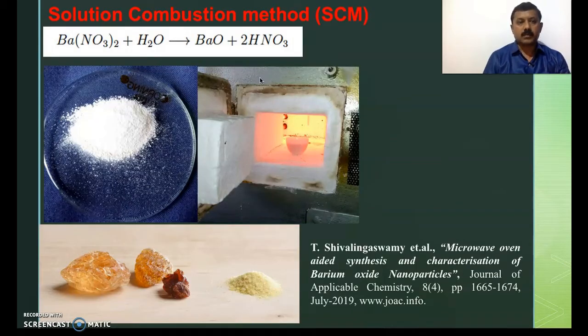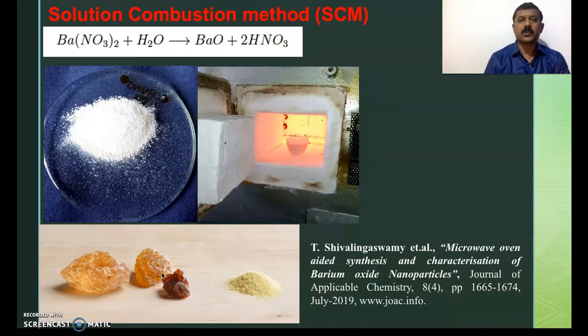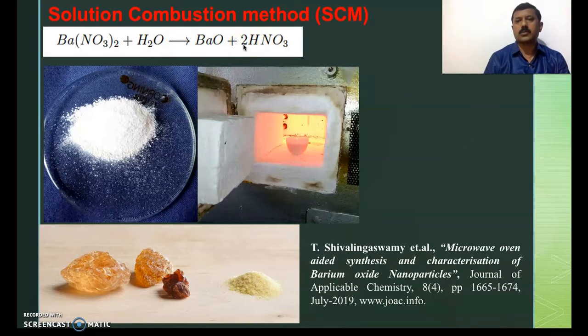As an example from the lab: barium nitrate was mixed with an appropriate quantity of water, and eucalyptus gum was used as the fuel. The gum solution was mixed in, and the mixture was heated in a furnace. Within two to three minutes, the reaction triggered, releasing nitrous oxides, and finally producing barium oxide nanoparticles.